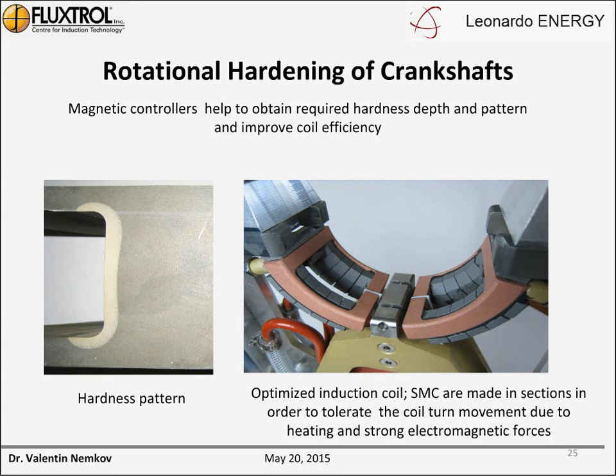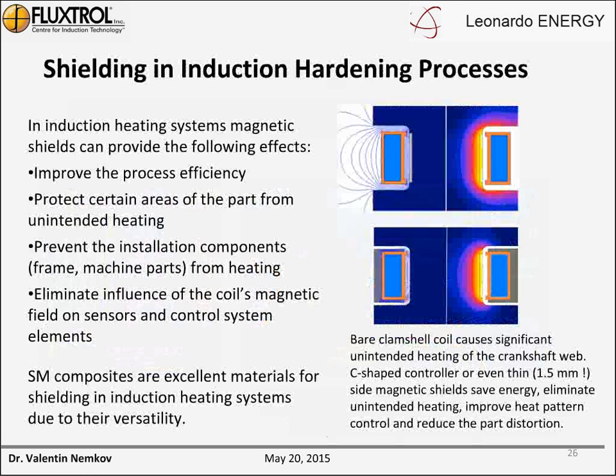Why in sections? Because these coils have very high power loading. And when you turn them on, the surface of the copper expands. Plus, we have strong electrodynamic forces. Because of that, we need to be sure that there will be no separation of the concentrator and the coil tubing. For that, it's good practice to make that in several sections. And on the left side, you can see very challenging hardness patterns that could be achieved with such coils. The other type of crankshaft hardening is hardening using a clamshell, which opens single turn coils.